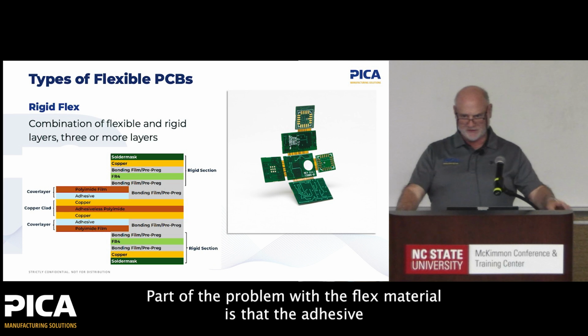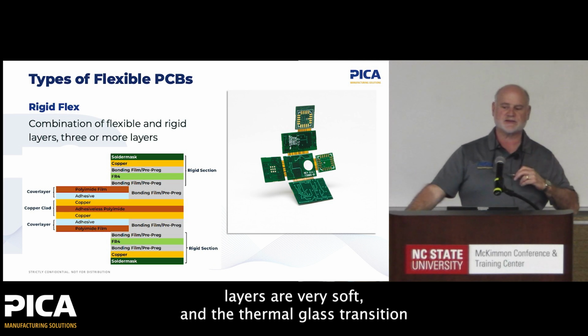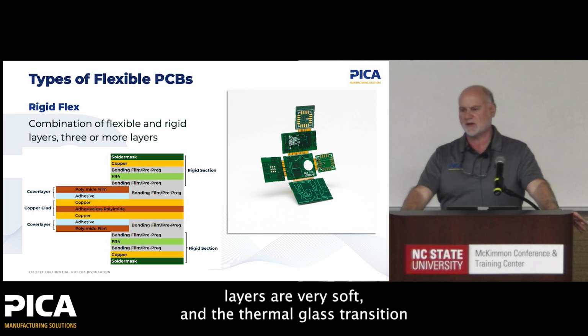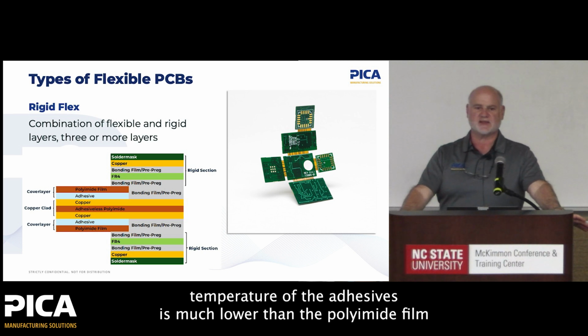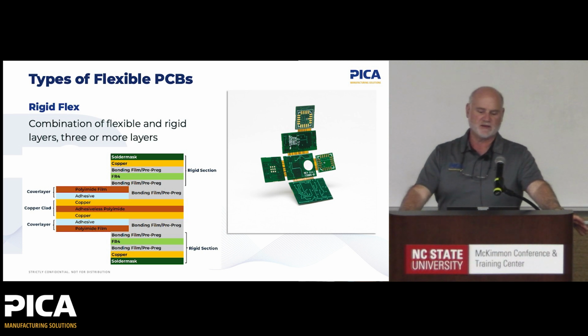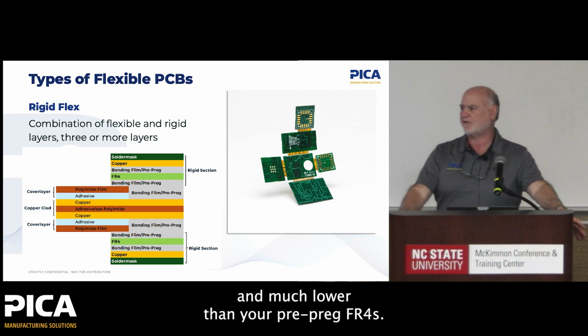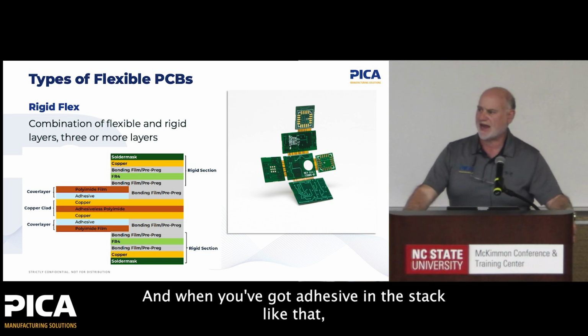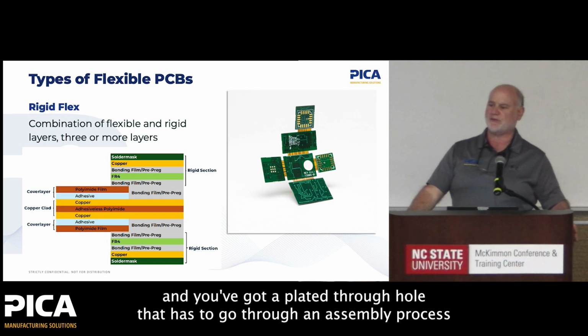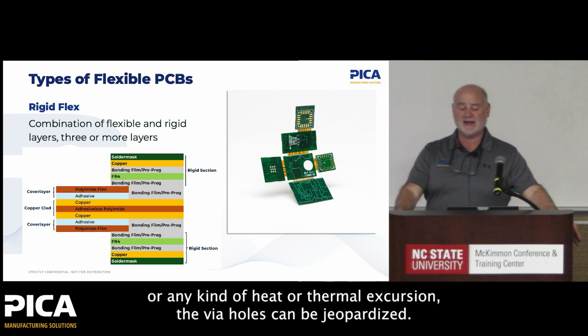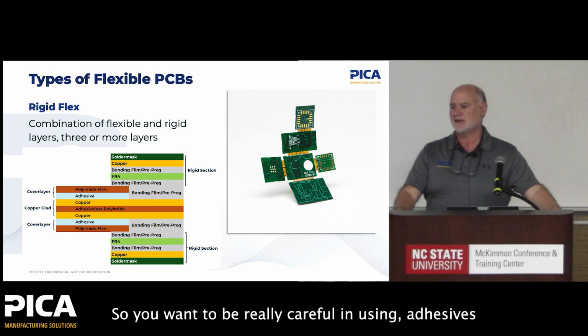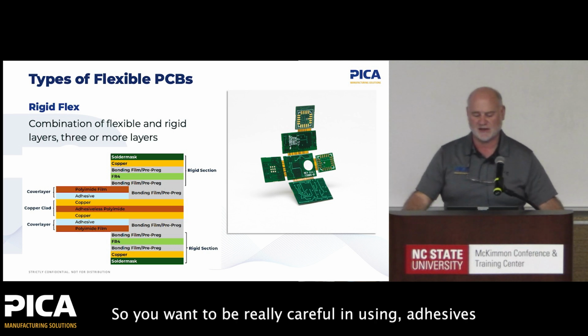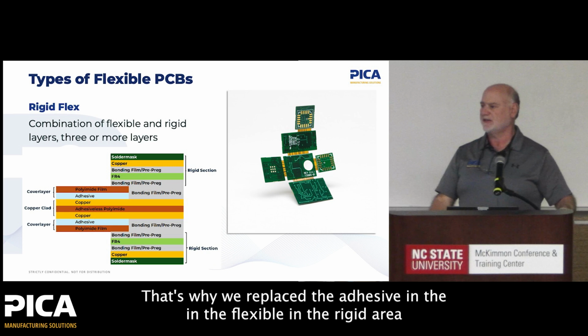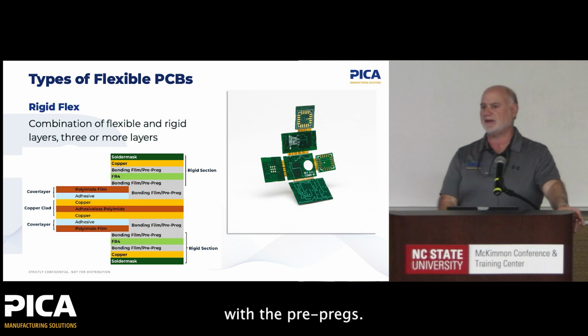Part of the problem with the flex material is that the adhesive layers are very soft, and the thermal glass transition temperature of the adhesives is much lower than the polyimide film and much lower than your pre-pregs or your FR4s. And when you've got adhesive in a stack like that, and you've got a plated through hole that has to go through an assembly process or any kind of heat or thermal excursion, the via holes can be jeopardized. So you want to be really careful in using adhesives through the stack up like that. That's why we replace the adhesive in the flexible and the rigid area with the pre-pregs.